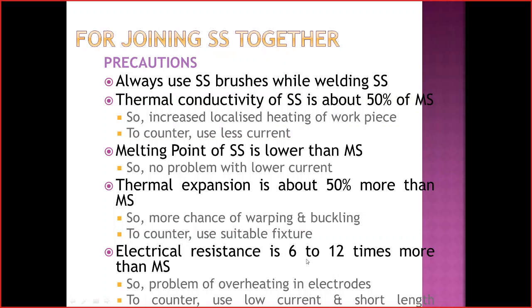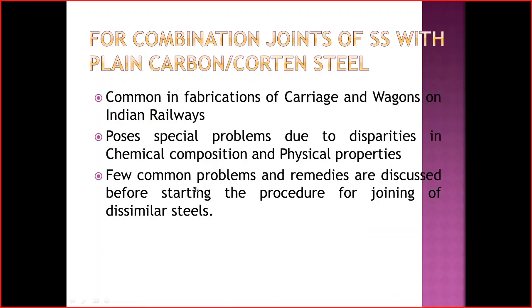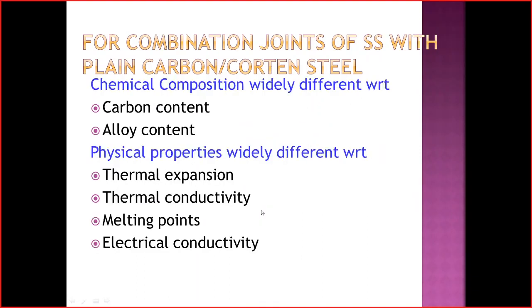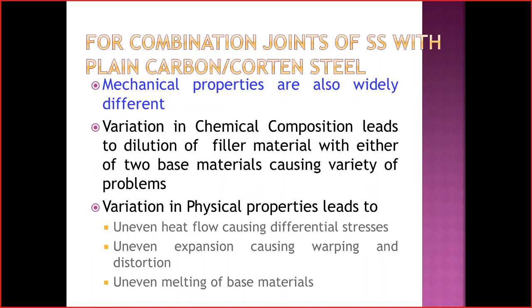And electrical resistance is 6 to 12 times more than MS. That is why there is a problem of overheating also. To counter it, you have to use lower current and shorter arc lengths. And for any other combinations, even SS with SS, we have to use some precautionary measures. These are all the things. Variation in chemical composition leads to dilution of filler metal with either of the two base materials, causing a variety of problems.